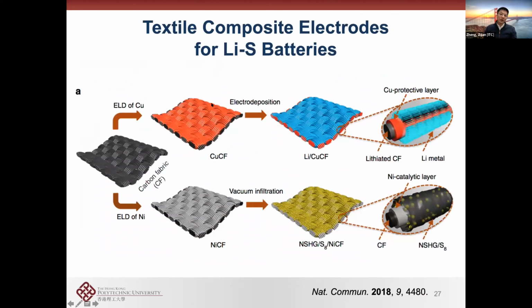So in this 2018 paper, we showed that you can use this idea to build very, very high energy density lithium sulfur batteries. At the same time, they're extremely flexible. So we started with a common fabric. We deposited copper or nickel. The copper is for the anode of lithium metal. Nickel is for sulfur. That's the sulfur cathode.